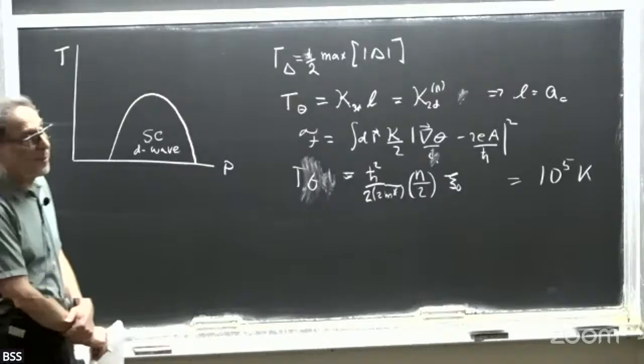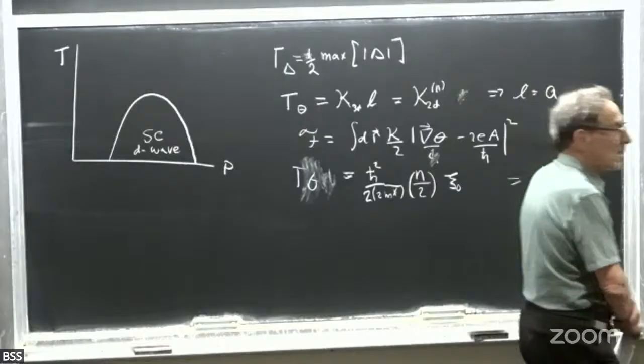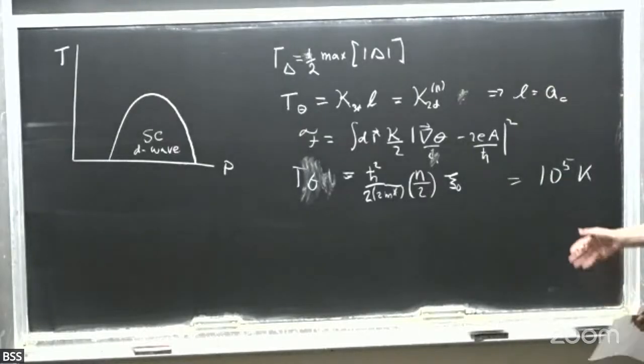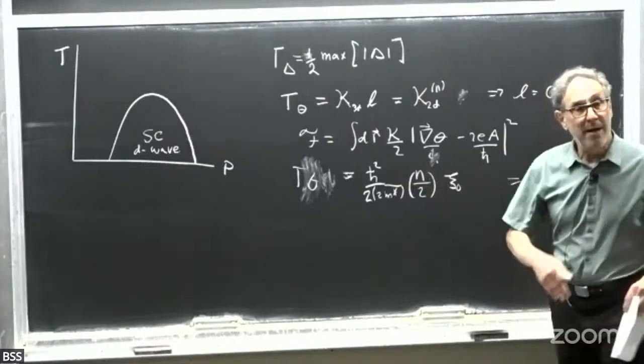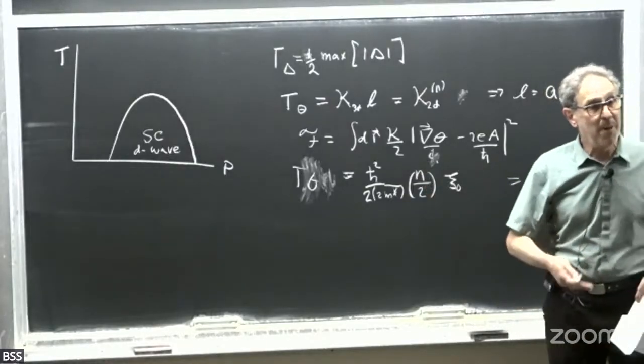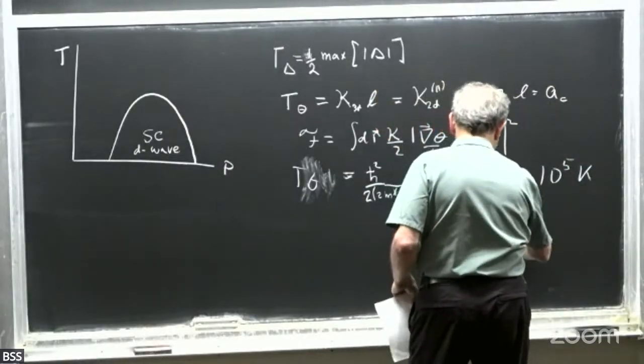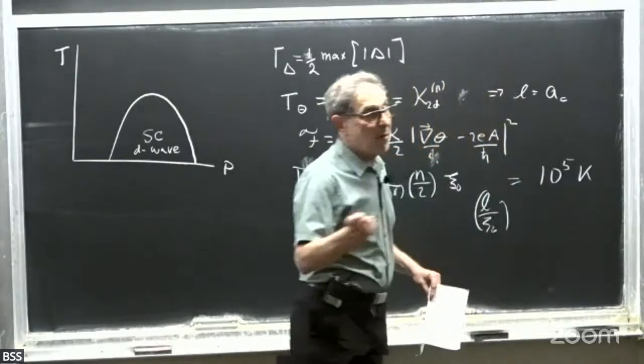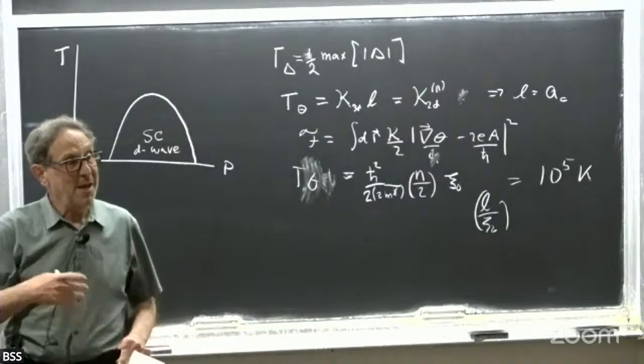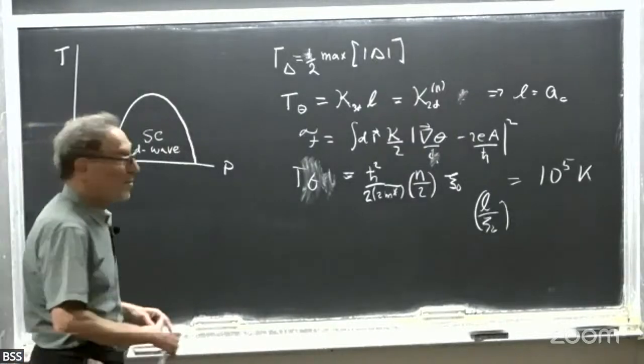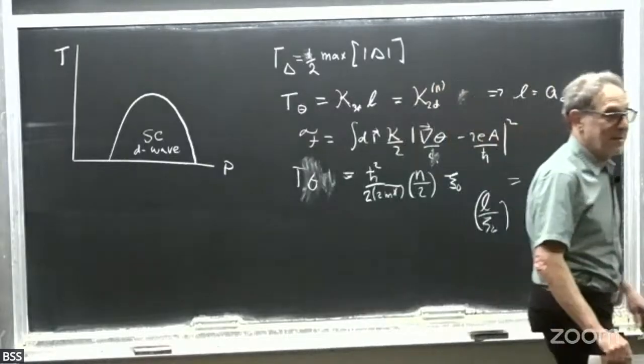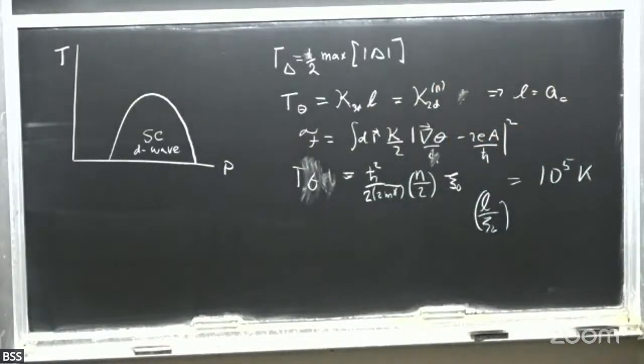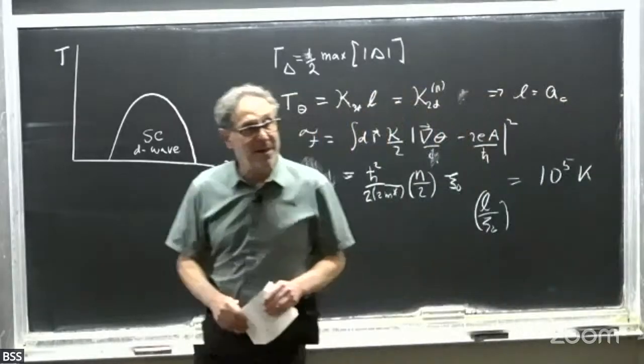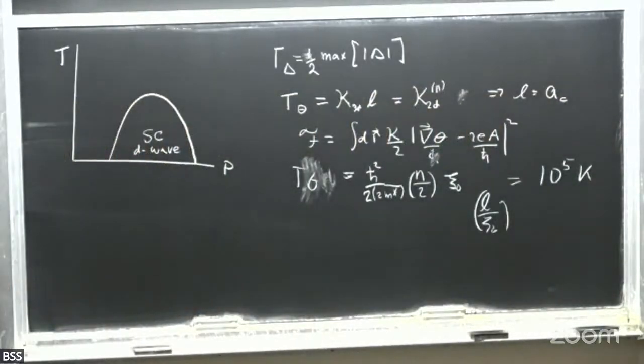So for a clean superconductor, use the full bounds. In a dirty superconductor, this will be reduced by a factor, the fraction of the electrons that condense, which is a fraction that's L over Xi naught. So if L is 10 angstroms and Xi naught is 1,000 angstroms, that's a factor of 100. That's still 10 to the third Kelvin. So you're just so far off in these numbers that there's no way in a conventional superconductor to make T theta matter.